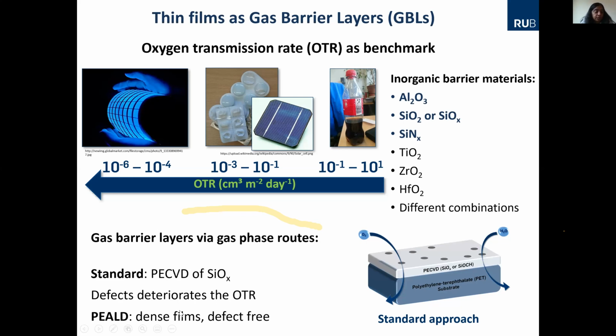So these defects, these pores, can deteriorate the OTR, because through these pores, oxygen or water can diffuse through and basically affect the inside material. So in that case, you need to avoid the pores, and ALD would be the method of choice, because you can have very dense coatings, actually pinhole free films, and you can get very good OTR values.